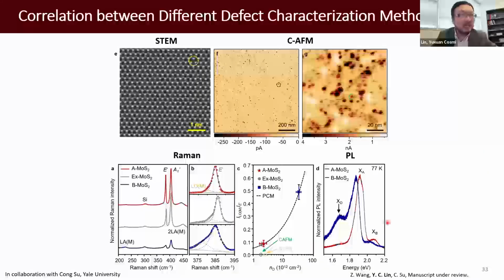We can compare that with other approaches. For the same sample, or samples produced by the same method, we compare the STEM, conductive AFM, and the Raman spectroscopy. For Raman, we use this side band of the E' peak in MoS2 to figure out the defect density. As you can see, it's already very weak.